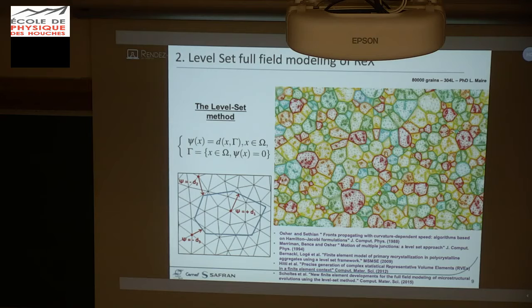The main difference between Voronoi and Laguerre-Voronoi is that with Voronoi you can respect a mean grain size, but not a prescribed grain size distribution. With the Laguerre-Voronoi tessellation, you can respect a grain size distribution.